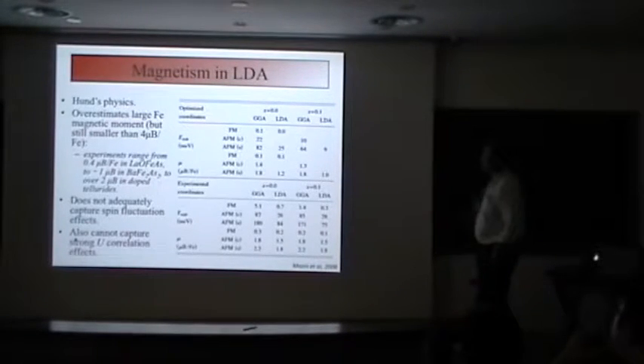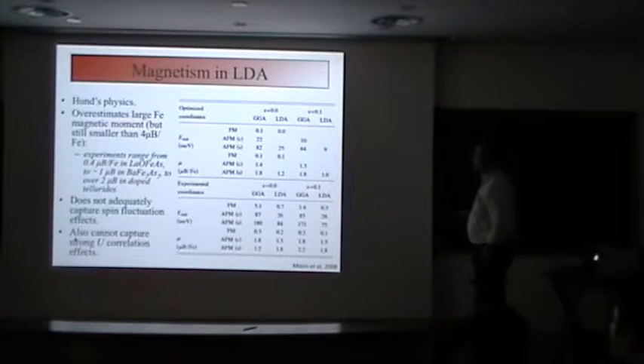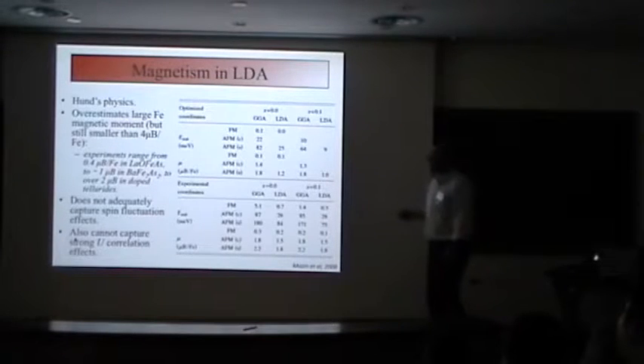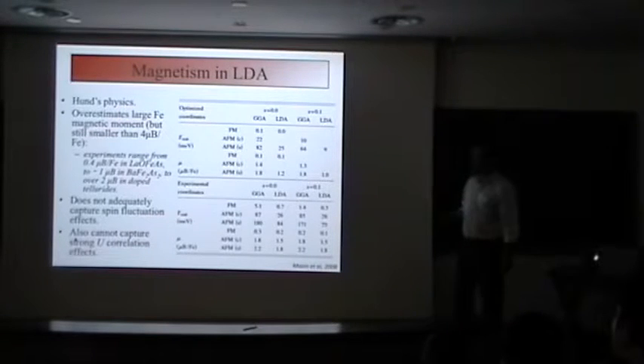Here's a table of different ways of implementing LDA using different approaches - the magnetic moment here using either optimized coordinates or experimental coordinates of the structure. You wind up seeing things on the order of around 2 Bohr magnetons per ion. This is smaller than the full saturation of 4 Bohr magnetons per iron, which is what you'd have if you just had Hund's coupling and no hybridization at all.